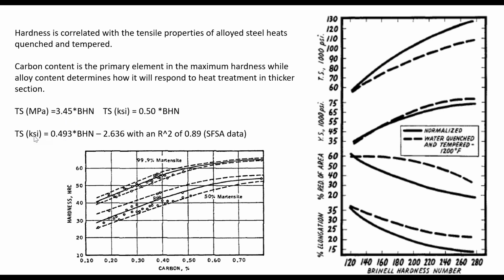If I take all of the quenched and tempered data that our members have given us, so that's like 9,000 points, I get this correlation. So I get a 90% correlation with a 0.493 Brinell hardness. So it really is a good relationship. That's the way we traditionally did it.